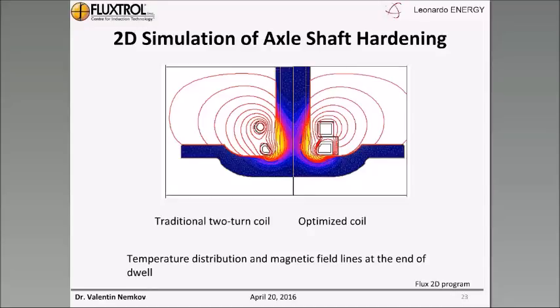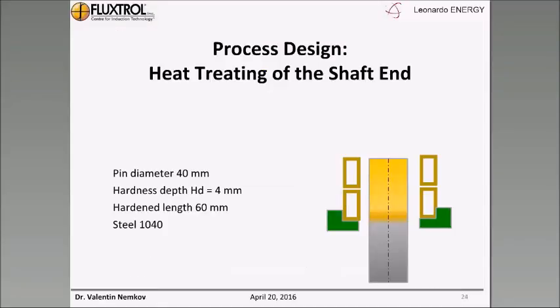One is that it's difficult to have proper heating of the flange, fillet area. If you want to have proper heating in this area, you'll overheat this portion of the stem, with a defect in the part. We designed a new coil, two-turn also, but with a different configuration of copper and the presence of a magnetic controller that can focus heating more on the flange without overheating this area. It's an example of 2D simulation.